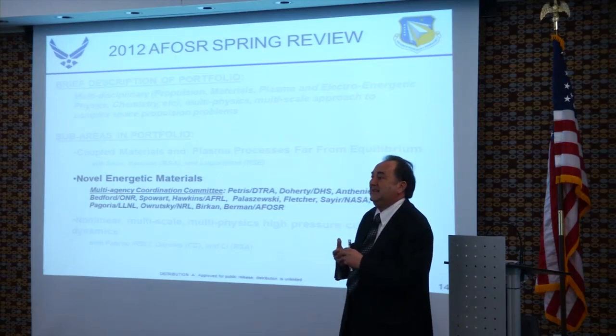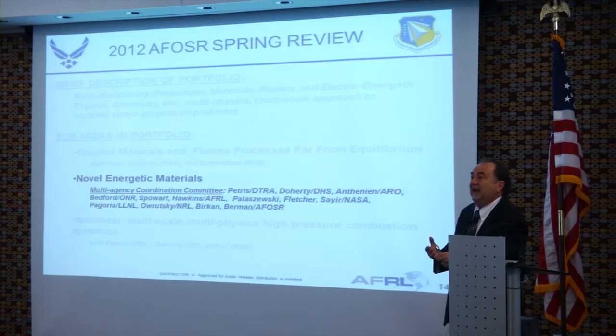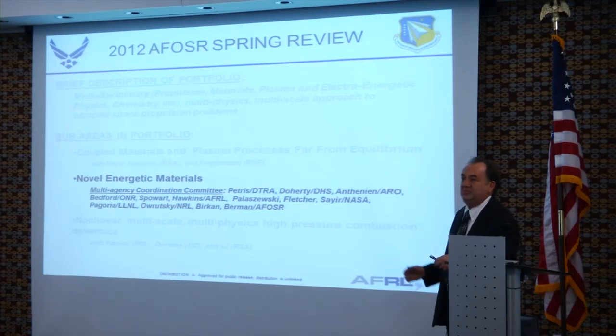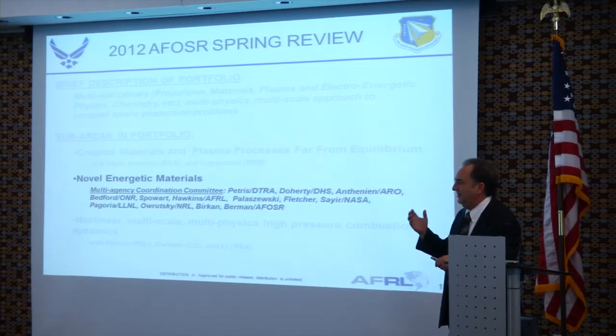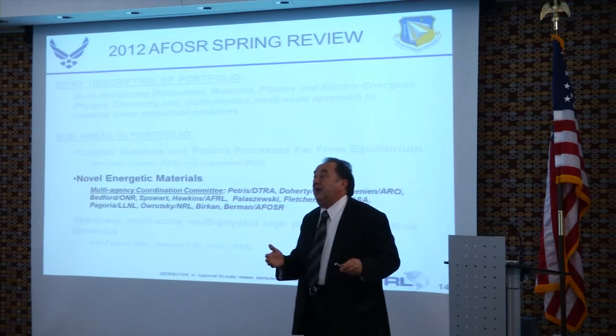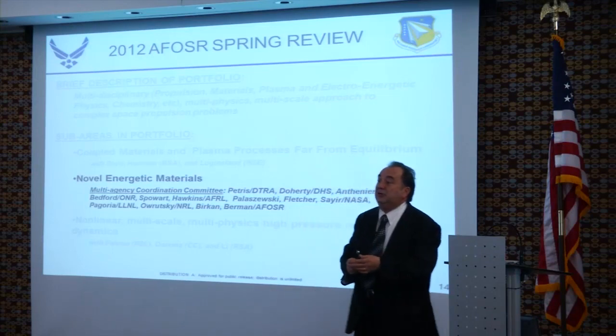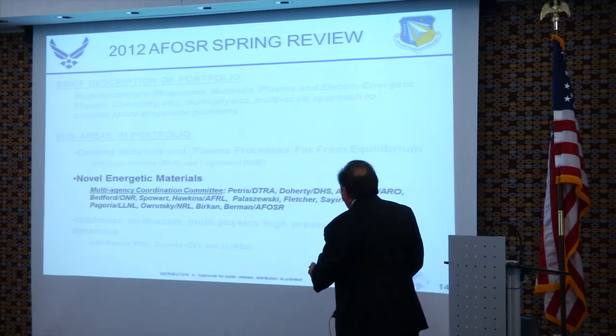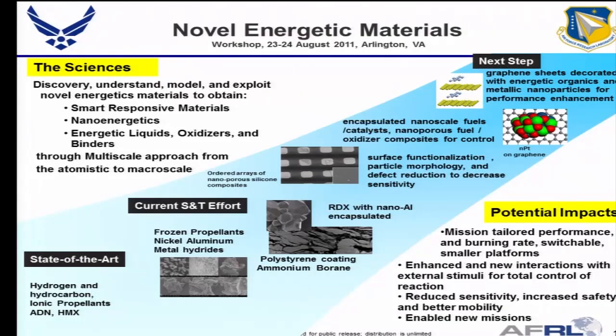However, if you are working in an explosive area, one would like to have a very rapid rise of the pressure, which is called brisance, I believe, a French word. And then they like to have very high detonation velocities. Also, in some cases, they like to have very low molecular weight products. Okay? Now, that means that in terms of propellants, intermetallics or thermites may not be the main ingredient because those produce very high molecular weight stuff. But they can be used as additives in order to control or tailor the ignition, sensitivity, and other stuff.